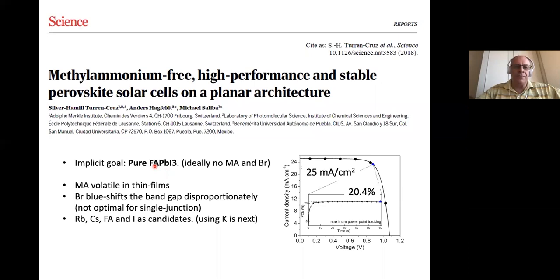There are two different reasons for it. One is that we don't want the bromide to increase the band gap, from the efficiency point of view. We don't want to have MA, which is more volatile than FA, because of stability reasons. So we really would like to come to this composition as the ideal band gap and the ideal efficiency. And in this work, we came fairly close. We got 20% efficiency. What we did here was to compositionally engineer, and we worked with cesium and rubidium on the FA site here.